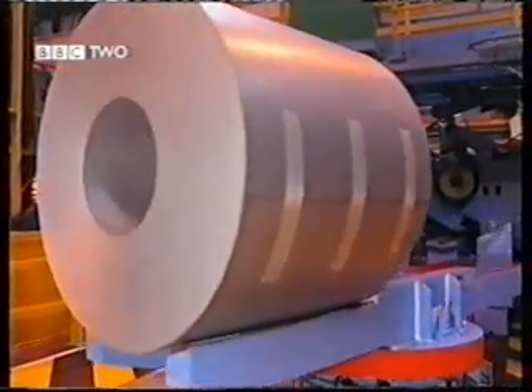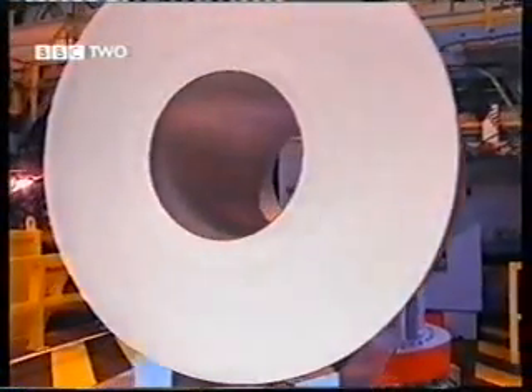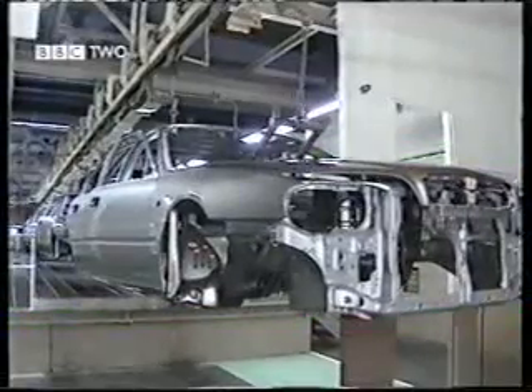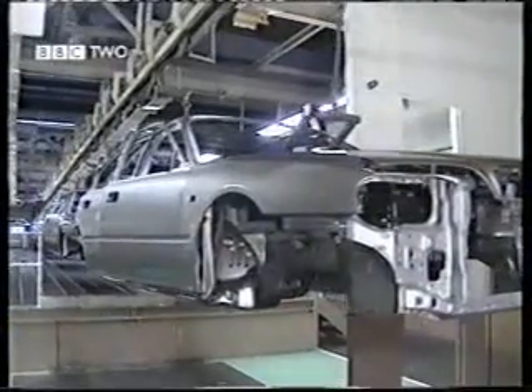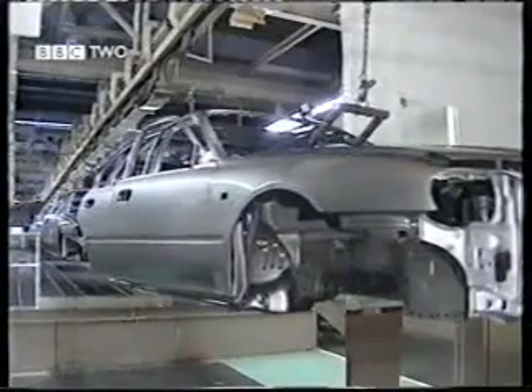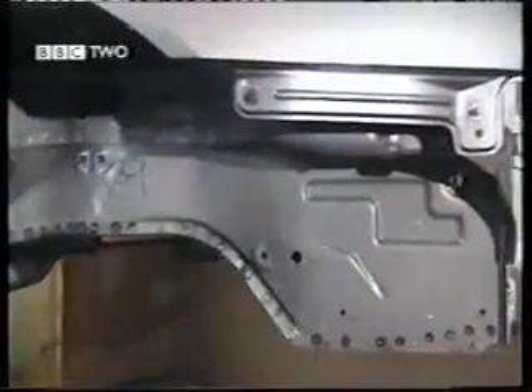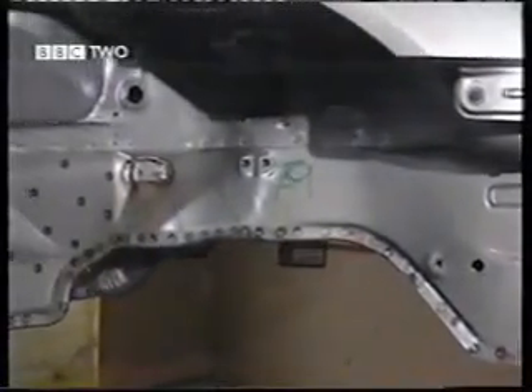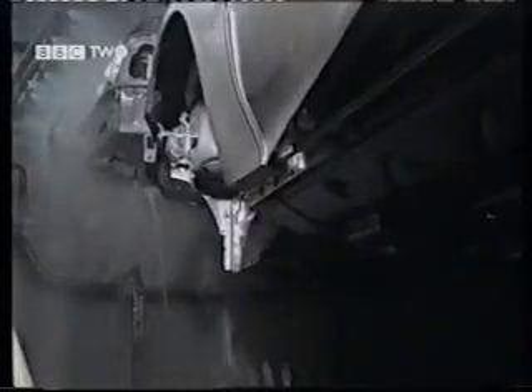The organic polymer layer is very like a paint. So let's look at what's involved in this traditional yet ongoing method of protecting metals from attack. After 331 panels have been given 4,500 spot welds, the body in white, as the industry romantically calls its creation, is given a thorough clean, including a hot bath in an alkaline mix of complexing agents and surfactants, followed by a cold rinse before treatment with a colloidal solution of titanium phosphate.